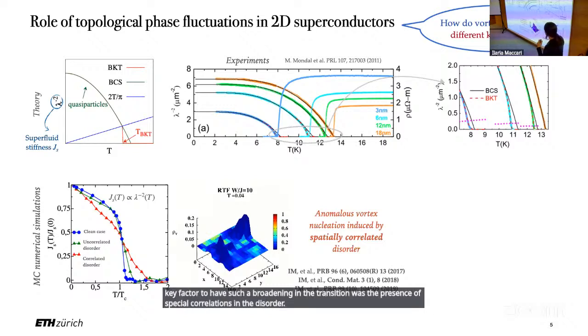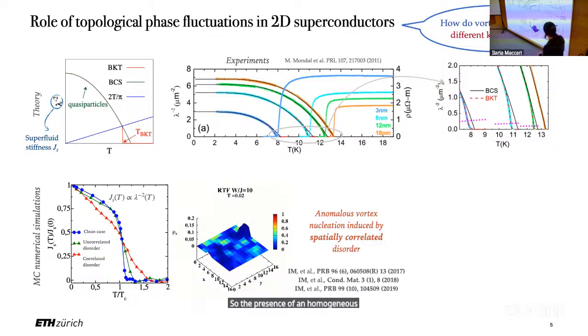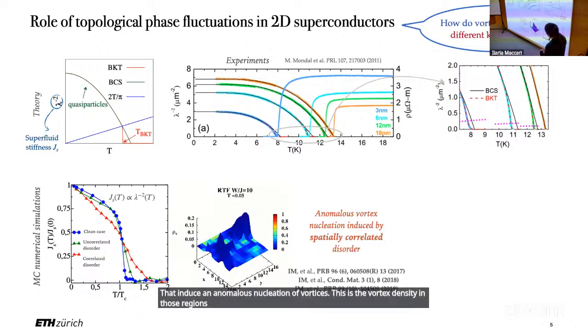So the presence of an inhomogeneous superconducting system induces an anomalous nucleation of vortices. This is the vortex density in those regions where the superfluid density is lower.